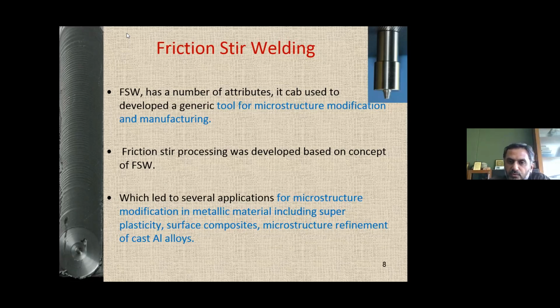Along with the rotary motion, the feed is given on a vertical milling machine, and you can see the joint formation, now you see there is no gap, right? And sometimes you can also tilt the tool to 1 degree, 2 degree for better consolidation of the material. Now you see here the tool is being tilted to about 1 degree or 2 degree. You see here. Now you see the joint formation has started at the back side, right? You see here.